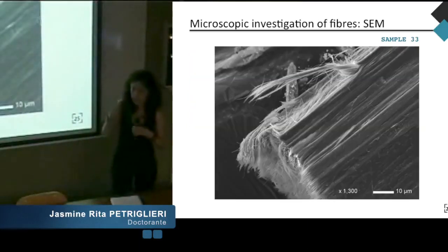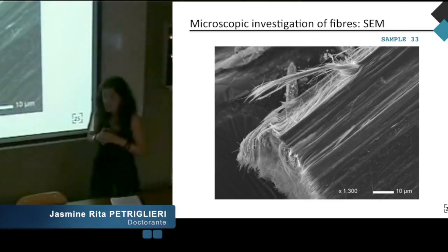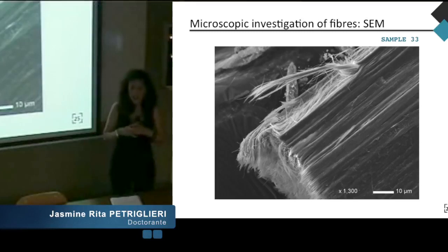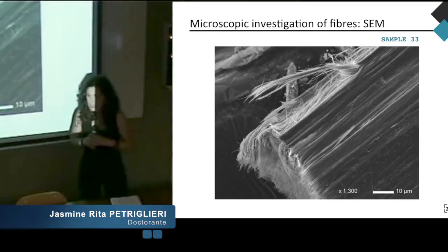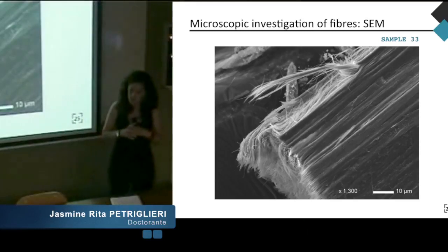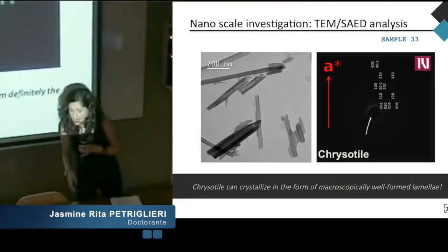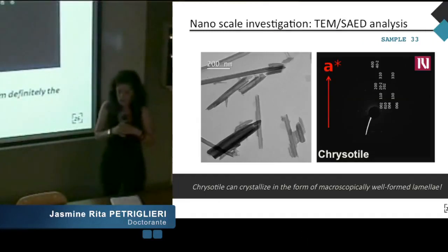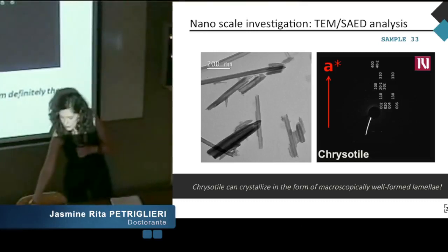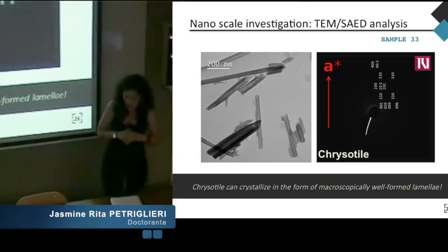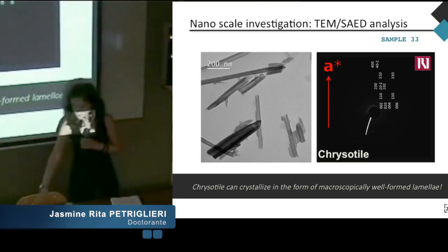For this reason, we decided to look further at the morphological nature of these samples, and the same images demonstrate the fibrous morphology of these samples. Finally, TEM associated with diffraction pattern confirms the identification of the chrysotile variety. It's so interesting that chrysotile can crystallize in the form of macroscopically well-formed lamellae.